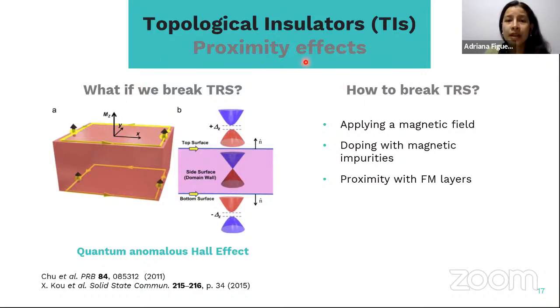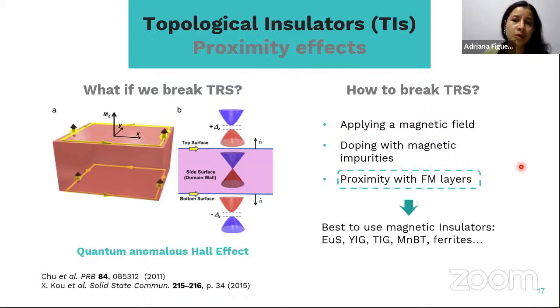Because it's interesting to study that there are some effects and some novel phenomena that arise at the interfaces of the TIs when we introduce magnetism, when we make these TIs magnetic, in order to break the time reversal symmetry in the system. For example, one relevant phenomenon that comes into play is the quantum anomalous Hall effect. And in order to observe this kind of novel phenomena and to break time reversal symmetry in the system, we can either dope the material with magnetic impurities or use proximity with ferromagnetic layers.